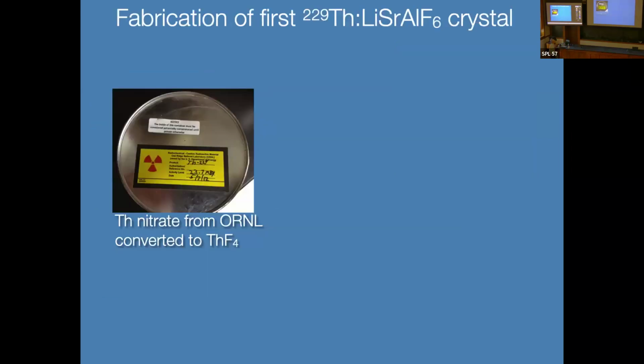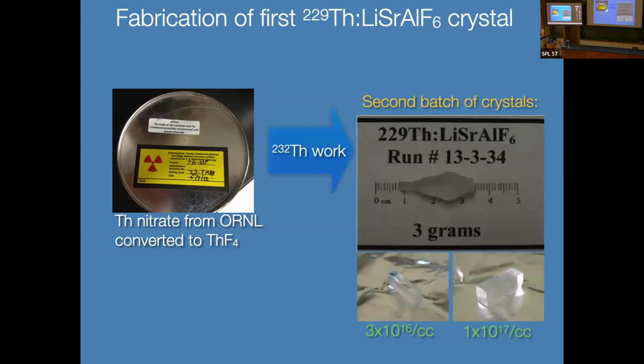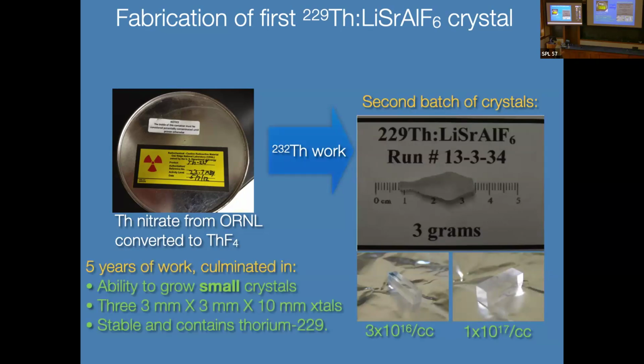But eventually, with a lot of help from our friends, we were able to solve this. Oak Ridge delivered to us that 3 grams of thorium. After about 5 years of work, we were finally able to grow these first thorium-229 containing crystals. So the crystal that we settled on for now was this lithium strontium aluminum fluoride.